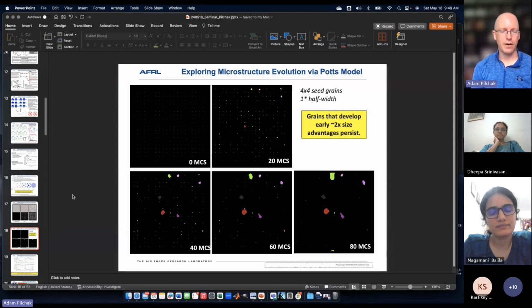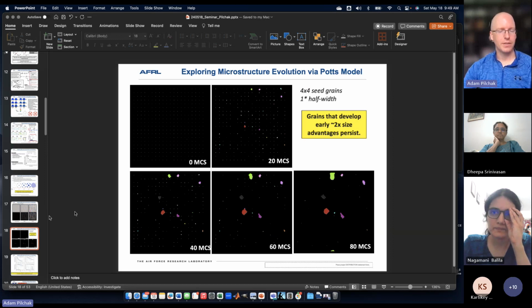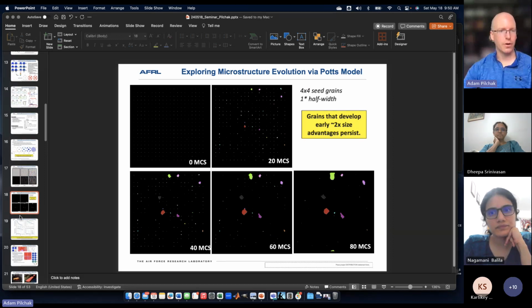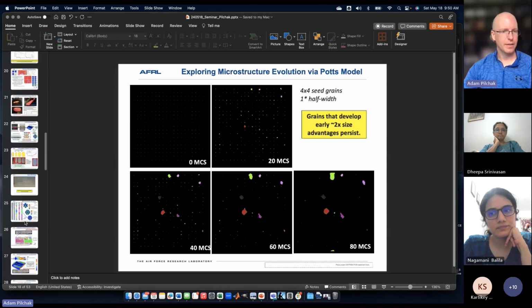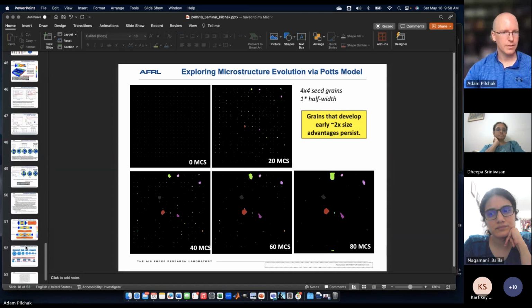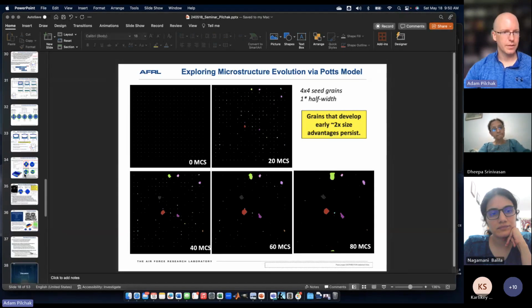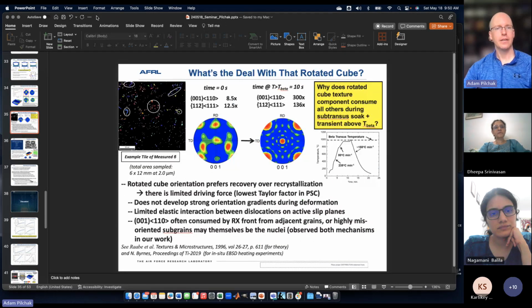No, this one was kind of off on its own. One thing that we had always wanted to do, so SPPARKS code also has a phase field simulator in it. And if I go back to my, now I lost it. This one. Yeah. One thing that I'd always wanted to do that we never got around to doing was to try to simulate the dissolution of the alpha phase and the growth of these underlying beta orientations. So SPPARKS definitely could handle that, because you do a phase field step and then a Monte Carlo step, phase field, Monte Carlo, which I think would be really interesting. But yeah, I have never linked it with the FEM work.